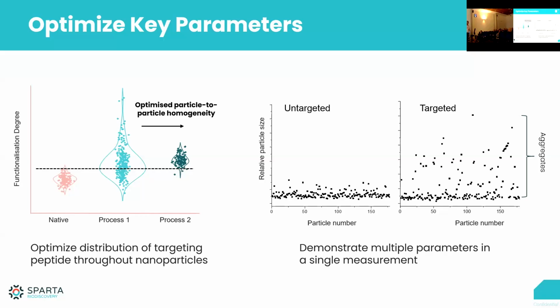And then with process one, this was kind of the first state of the formulation. So we can see a pretty decent amount of particles have the targeting ligand on, but it's very, very variable. And then when they optimize the process, you can actually bring that variation down massively and have a very tight control over the amount of targeting ligands inside a formulation. And SPARTA can really help you show that that's the case, and the difference there. Again, between process 1 and 2, there is a marginal difference in the mean that you would have with a bulk technique, but of course, a massively different insight on a single particle level.